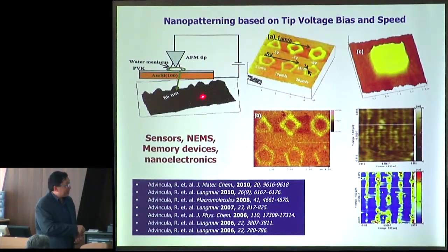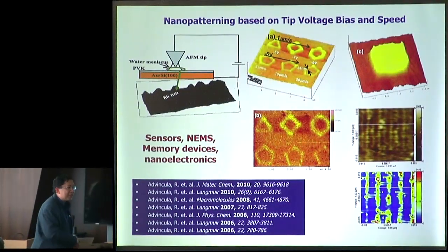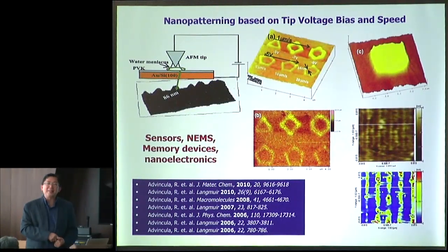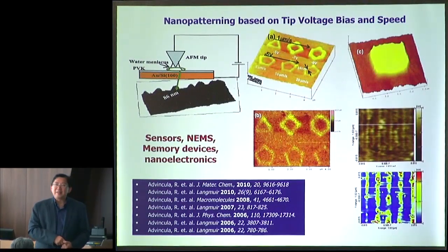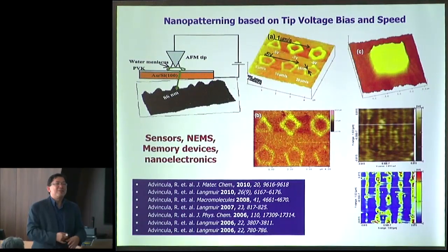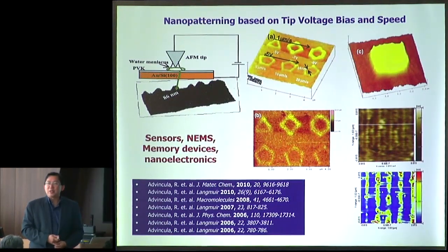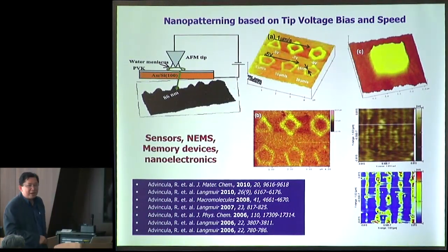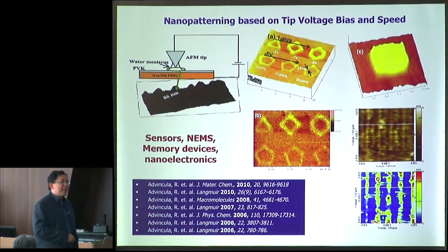In fact, we verified the presence of this high humidity environment by doing the same experiment in vacuum. We did it in vacuum, no result. We reduced the humidity to 5%, no result. But when we do it in a room temperature environment, everything worked very well. So it's the simplest method to nanopatterning, electronanopatterning.